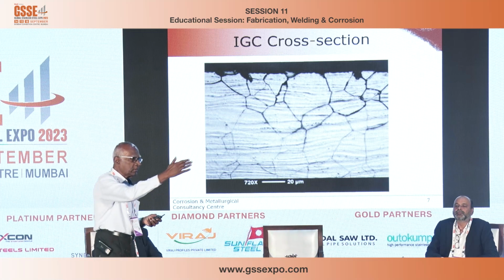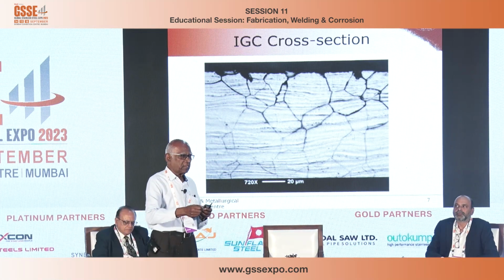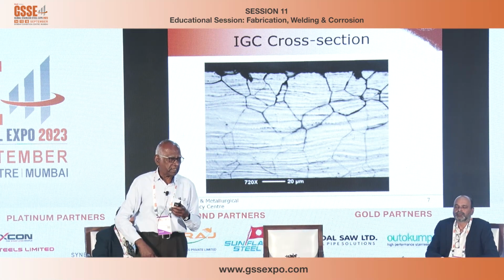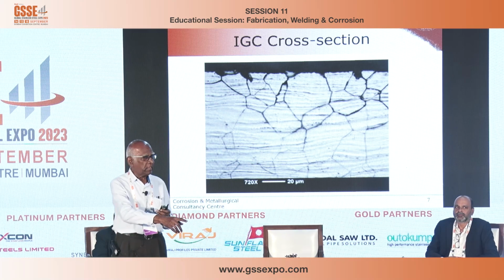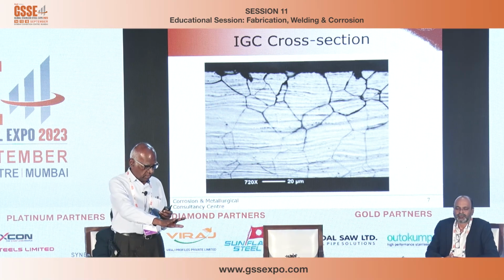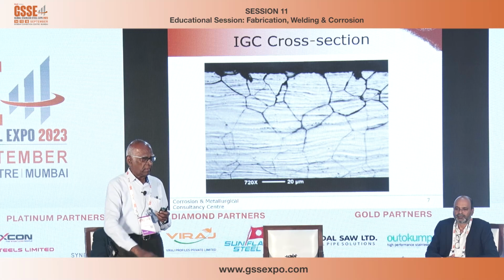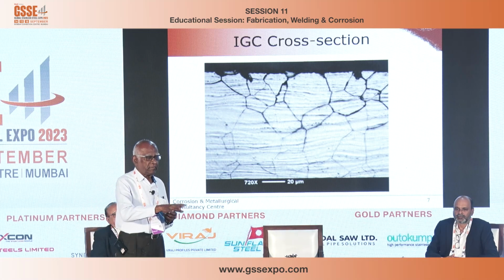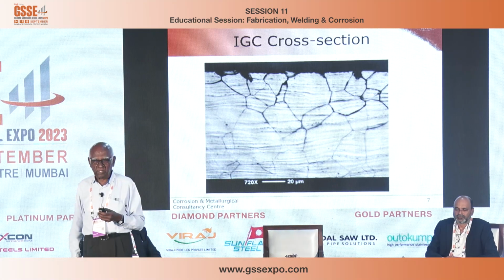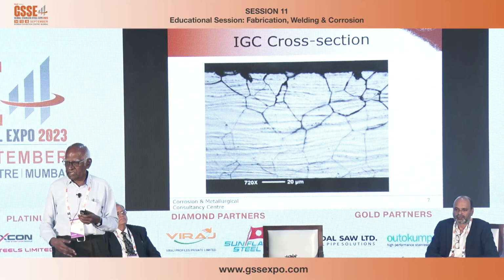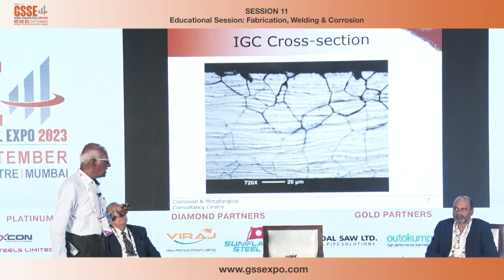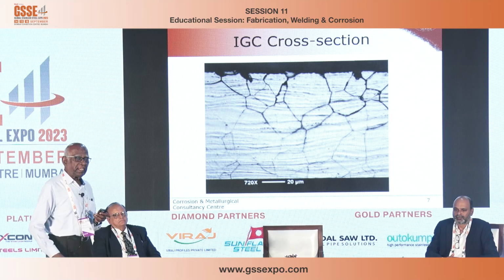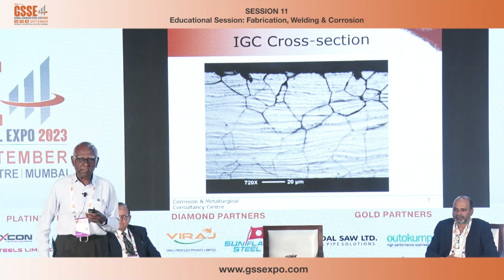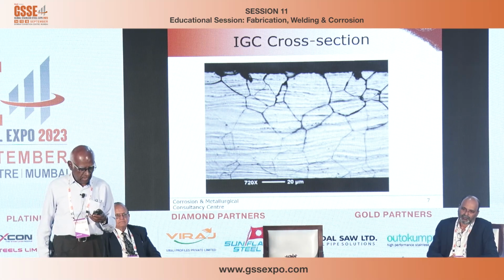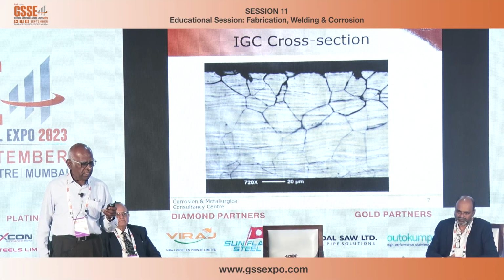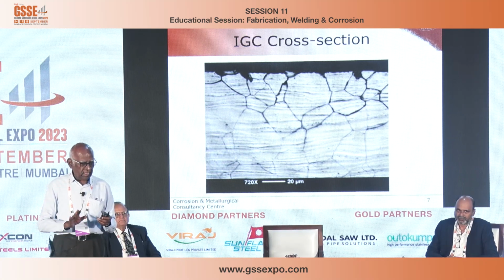So if you go to a company and bring an ultrasonic wall thickness detector, it won't show any loss of thickness, but corrosion is there. So this is very important. It's a localized corrosion. It is not a wall thickness reduction. It is very, very localized corrosion without showing any NDT value for thickness reduction. So all these can occur near a weld joint.